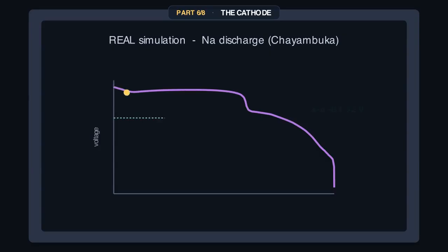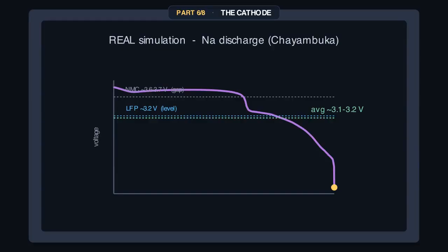Now remember that third of a volt from the metals? That's a same-cathode statement. Build a lithium cell with the same kind of cathode, and sodium sits about that much lower. But real cells use different cathodes. Against lithium iron phosphate at 3.2 volts, sodium is nearly level. The big voltage gap only really opens against nickel-rich lithium up near 3.6.